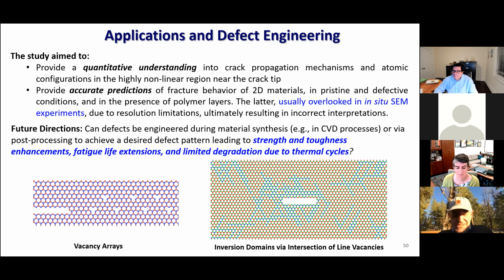The question is concerning your comment about the effect, or if you like, lack of effect of vacancies on toughness. You were kind of disappointed. That's the way it sounded. But if I think about this lattice as a structure as opposed to a material, sometimes we call this lattice a Kagome lattice. I don't know if that's quite right, because you actually have the hexagons rather than the triangles as well. But I'm thinking that this looks like a structure that is almost statically determinate. So there isn't a lot of scope, I think, for tuning the local stress distribution, and hence I don't know that you can actually hope to achieve a lot with this particular scheme.